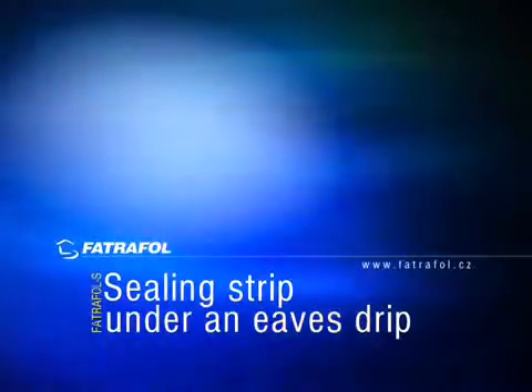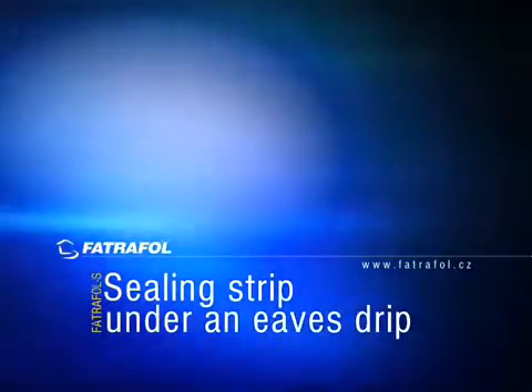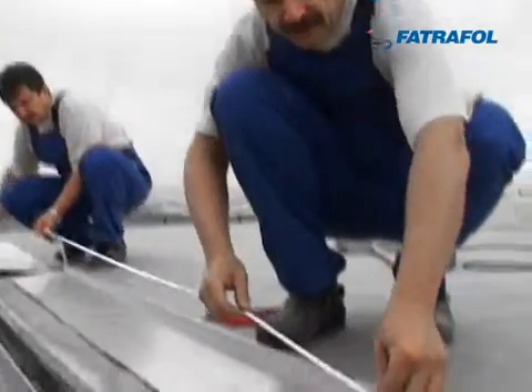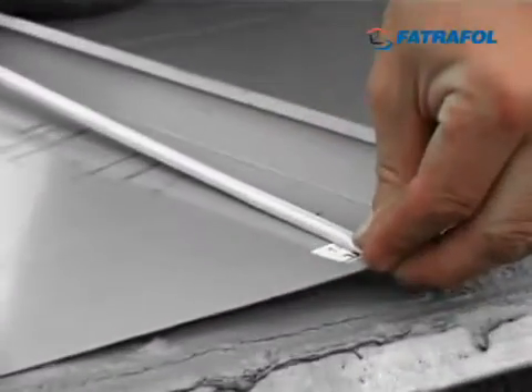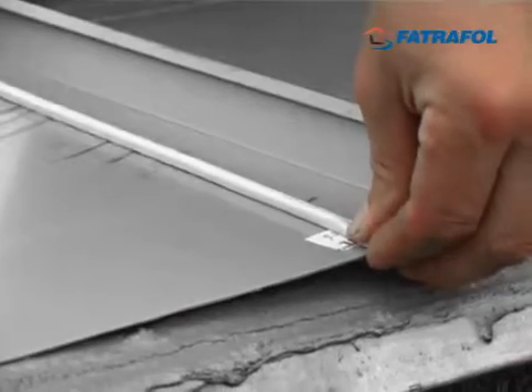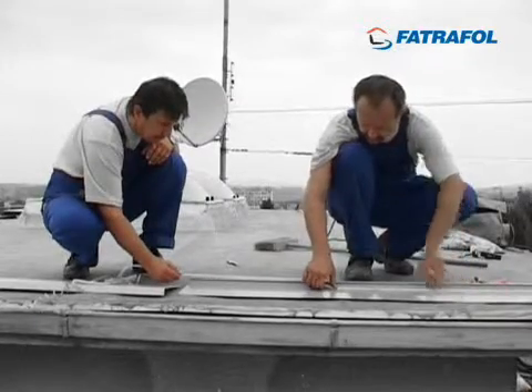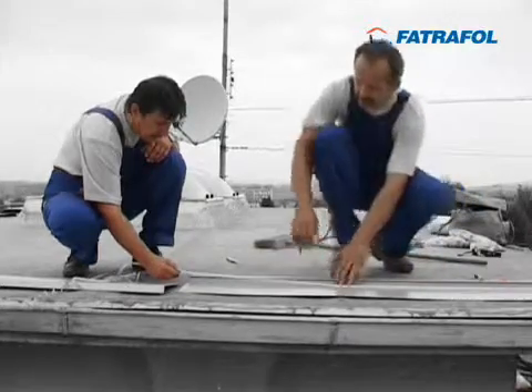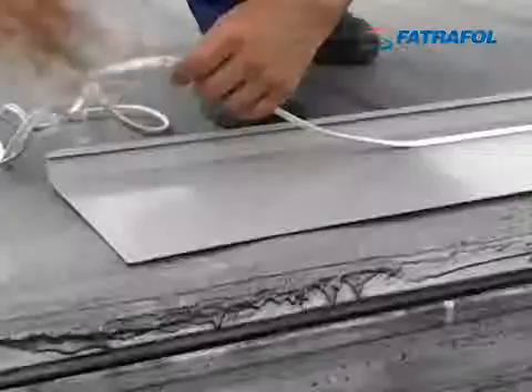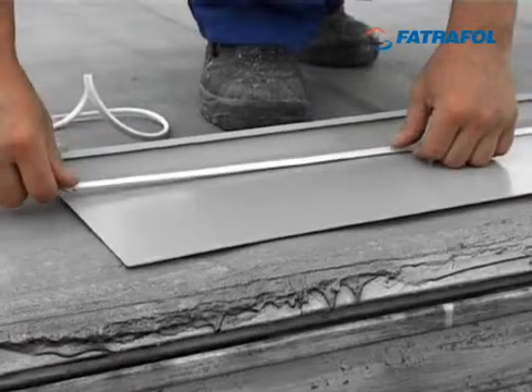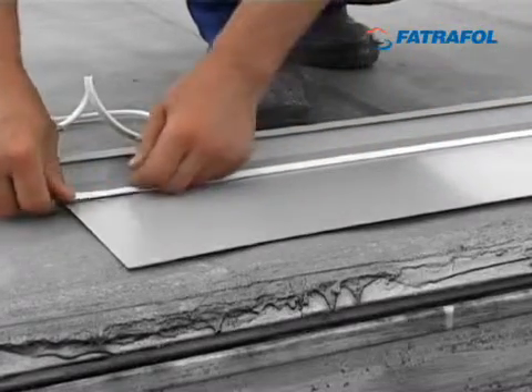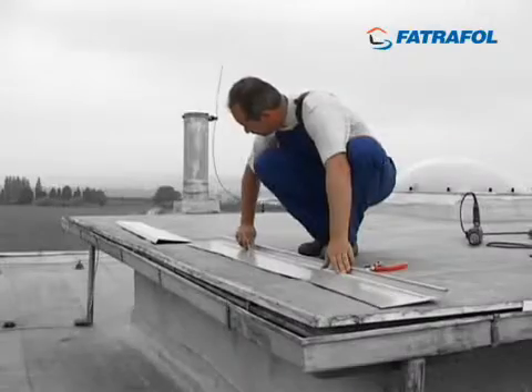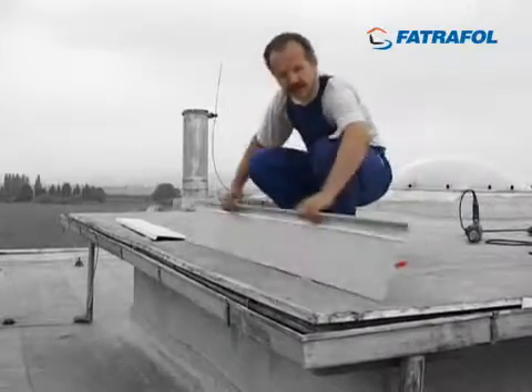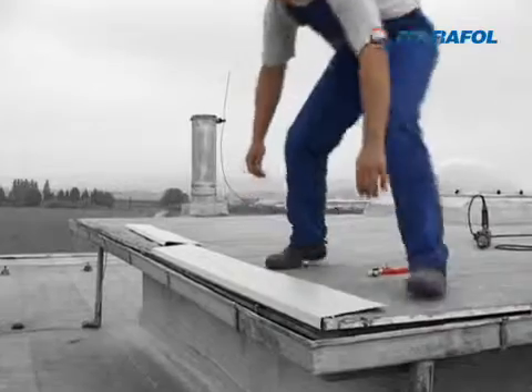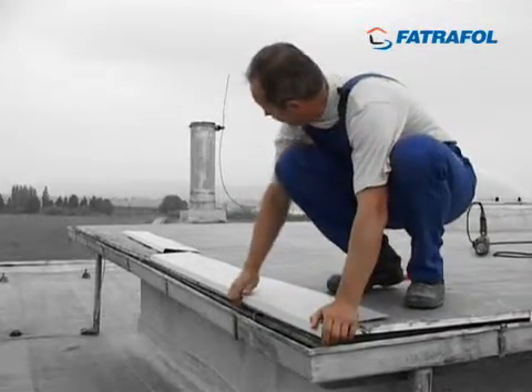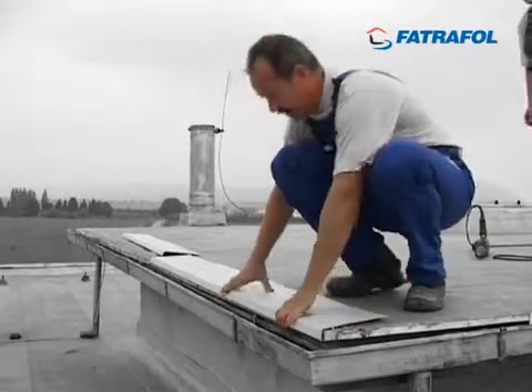Sealing strip under an eaves drip. Having cleaned and tidied the roof, you can now install the PVC coated metal profiles on one pre-selected site. If reconstructing a roof deck with uneven edges, we recommend to proceed as follows. Glue the sealing profile, made of microporous rubber or lightweight polyethylene, onto the underside of the eaves drip. This will prevent wind from blowing under the roof covering and provide for effective removal of water vapors from individual structural layers of the roof deck.